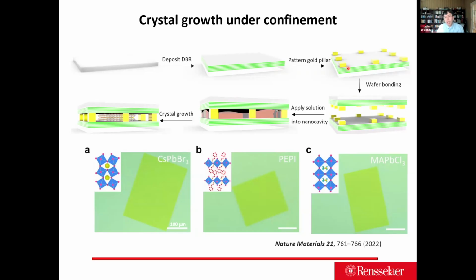But after the wafer bonding, when we cut into small dies, each die only occupies a small area of the wafer, so the sample variation in thickness there is much less. We quantify it at about 0.5%. Afterwards, we apply a solution of the perovskite and run the crystal growth for a really long time. In our case, it's two to three days. We let the material gradually grow in the cavity, and we can grow cesium lead bromide, the layered perovskite PI or PEA-PI, depending on how you name it, and MA lead chloride samples with sub-millimeter size. We can further grow them, but sub-millimeter size is already really big for polariton physics study.